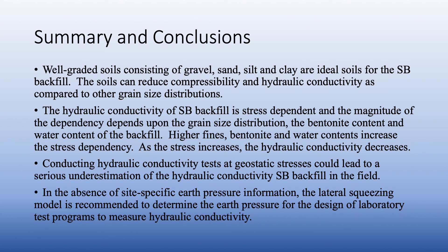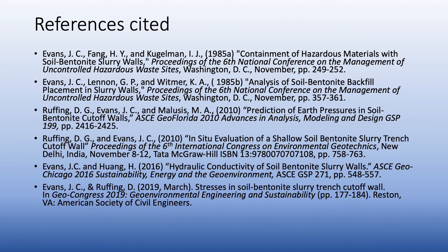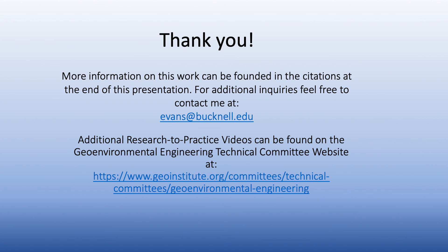Conducting hydraulic conductivity tests at geostatic stresses can lead to a serious underestimation of the in-field hydraulic conductivity of soil bentonite backfill. In the absence of site-specific earth pressure information, the lateral squeezing model is recommended to determine earth pressure for designing the laboratory test program. More information can be found in the cited references and by contacting me at evans@bucknell.edu. Additional research-to-practice videos are available at the geo-environmental technical committee website. Thank you very much for your attention.